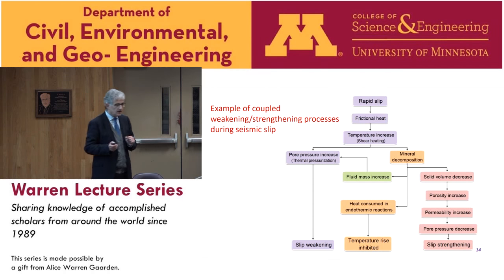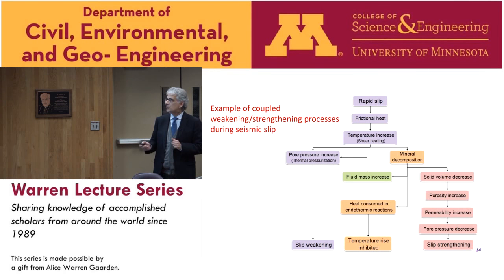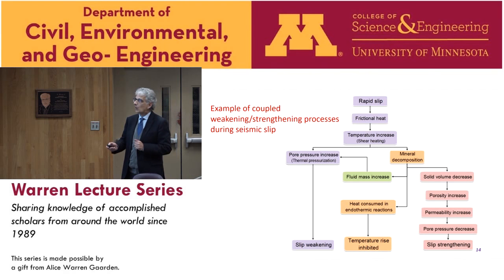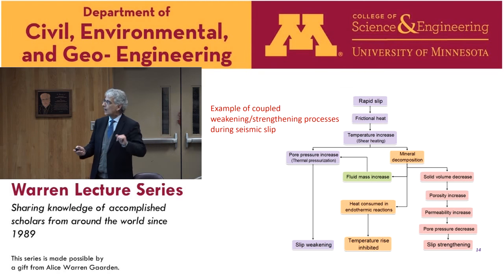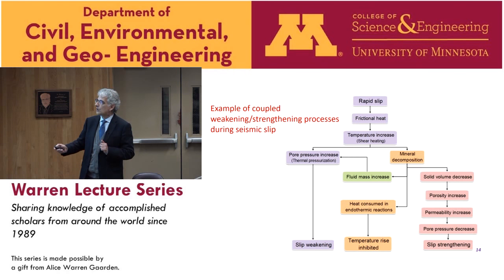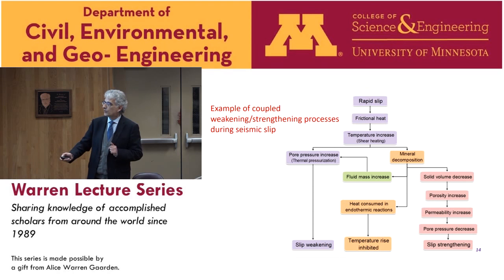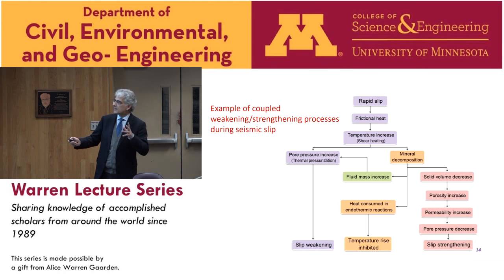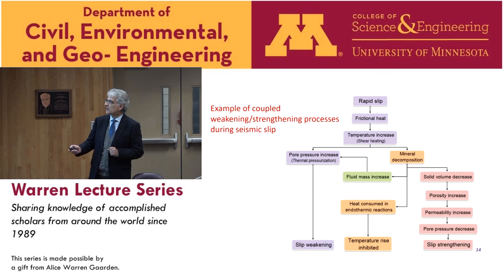So if we summarize these processes, we have rapid slip, which produces frictional heat, causing an increase of temperature. On one side, we have thermal pressurization of the pore fluid, a pore pressure increase, which is a mechanism of slip weakening. If the temperature rise is high enough, we have mineral decomposition with a release of an additional fluid mass, contributing to more pressurization of the fluid, so to stronger weakening. But on the other hand, in a competing effect, there is a solid volume decrease, an increase of porosity and of the diffusivity, which can cause a decrease of the pore pressure. And this is a mechanism which can induce slip strengthening as opposed to this one. And the heat which is consumed in the endothermic reactions will inhibit the temperature rise.